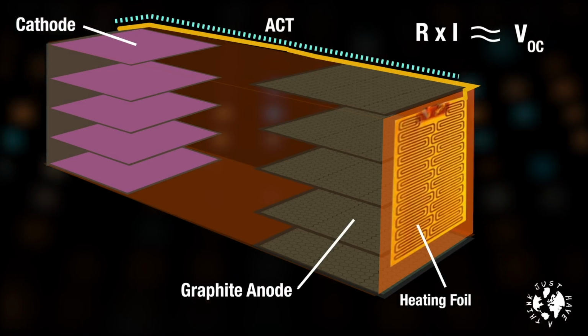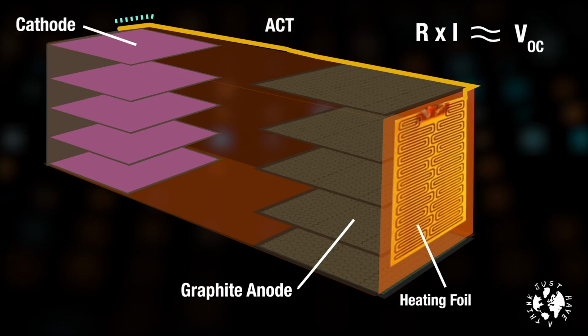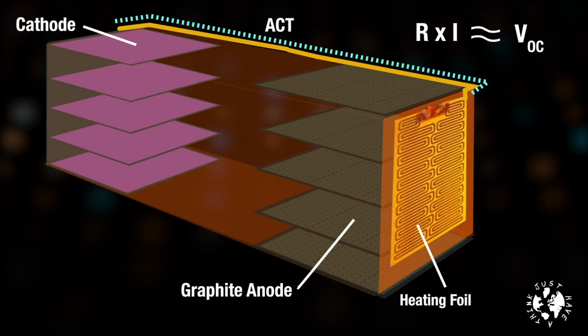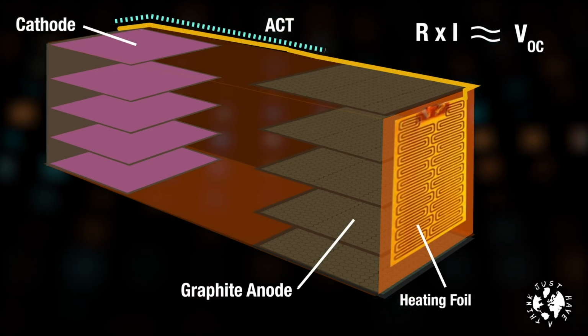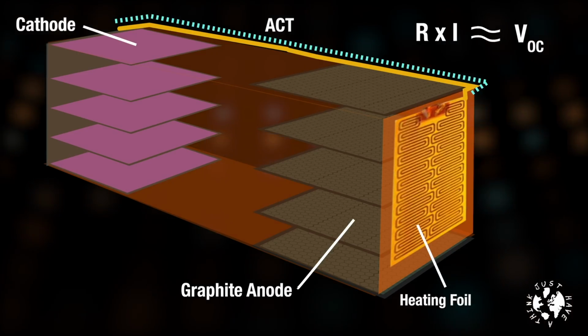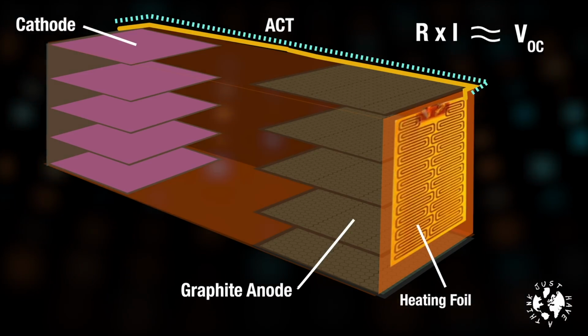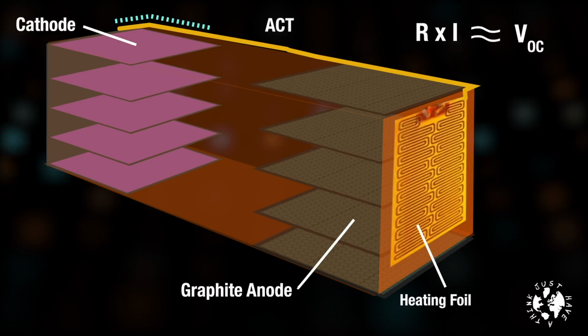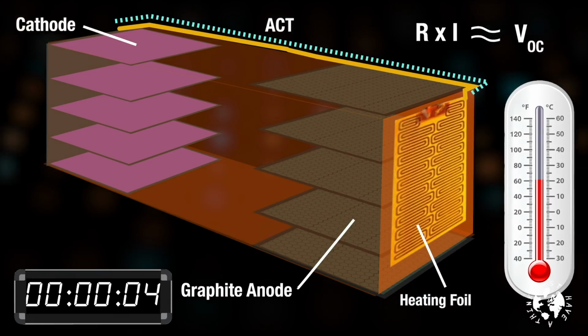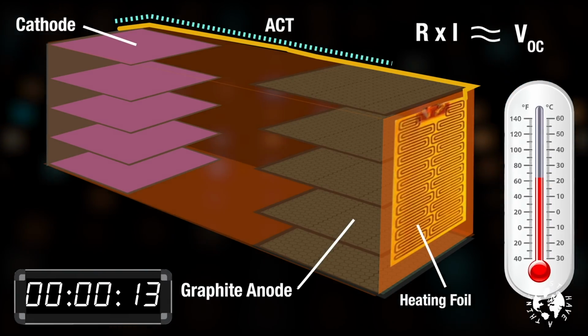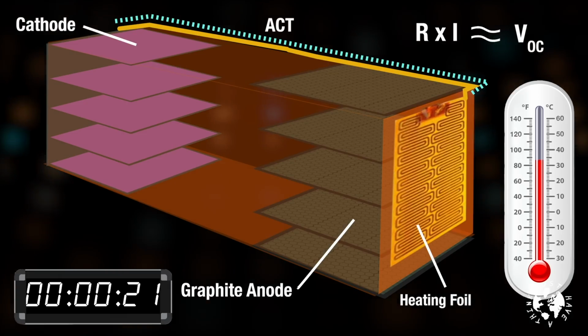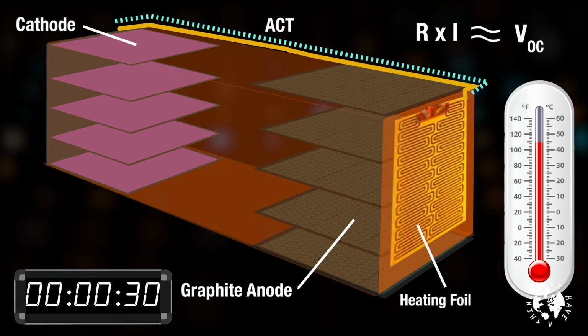The team used a current of 57 amps for the charging cycle, and most of that current, at least for a brief period, is channeled straight into the nickel foil. That's a very high current going through very thin foils, and the consequence is immense heat, warming up the cell from about 21 Celsius to 45 degrees Celsius in just 30 seconds.